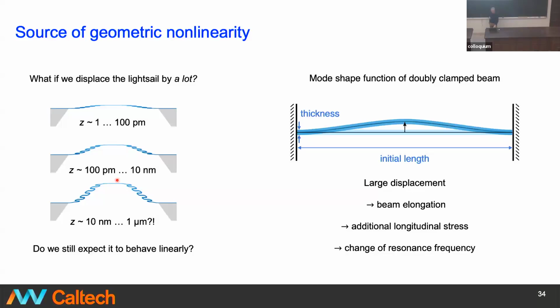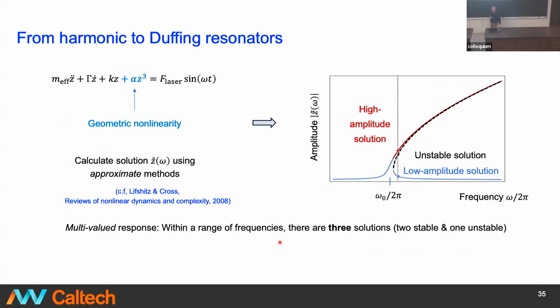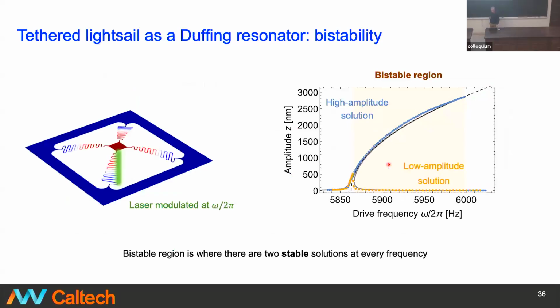At resonance, I can see large displacements, and there will be beam elongation. There will be nonlinearities that come in from purely mechanical reasons that give rise to changes in the resonance frequency. That gives rise to bistable and nonlinear excitations. We have so-called Duffing oscillations. Our forced damped harmonic oscillator now has, in addition, a cubic dependence on displacement. Then there are two modes, a high amplitude and a low amplitude solution. If I excite at resonance and change the excitation frequency from the mechanical resonant frequency, I can drag, so to speak, the forced oscillation off its resonance frequency until it lets go, snaps back, and recovers into the low amplitude solution. That represents a bistable trajectory that we can see.